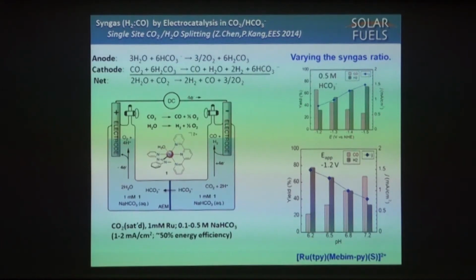So in this experiment, what we did is we put the same catalyst on both sides of the electrochemical cell. There is an anion exchange membrane between them and a connector. If you apply a potential, and this is all done in aqueous solution, no acetonitrile. In the end, all of this has to be done in water. The reactions have got to be done in water, just because they have to be on a massive scale. If you look at that, the net reaction is water plus CO2 doing what? One of our targets, syngas. Oxygen comes out of the anode. Combinations of hydrogen and CO come out of the cathode.